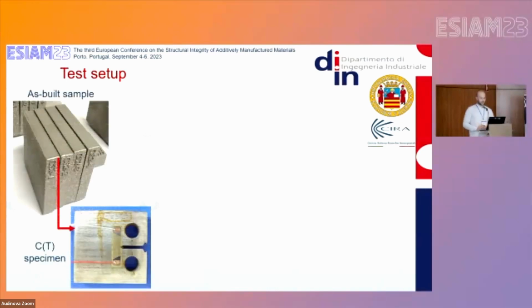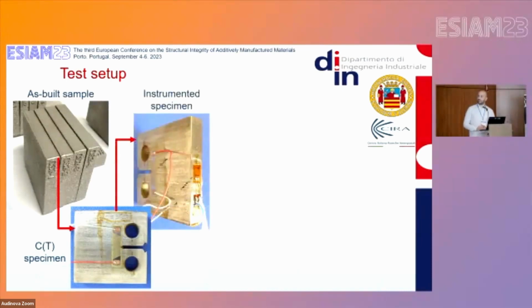For what concerning the test setup, we started from the as-built sample, and then we manufactured the specimen. So we created the notches and the pins. Then we instrumented the specimen, and we can see in this central figure that we considered 2 measurement systems. One is based on a crack gauge glued on the side of the specimen. Another measurement system is based on a strain gauge that is positioned at the back end face. These sensors, the one on the right side, allowed us to measure the strain during the process. With this strain, we were able to calculate the actual crack length during the propagation.